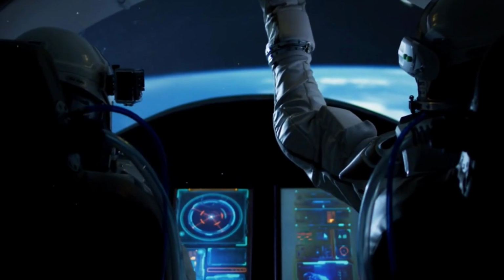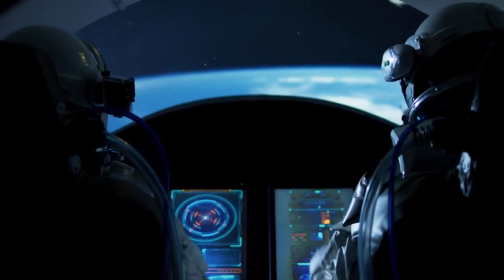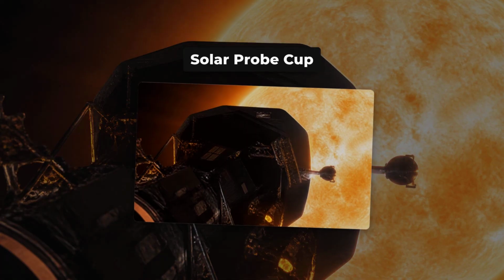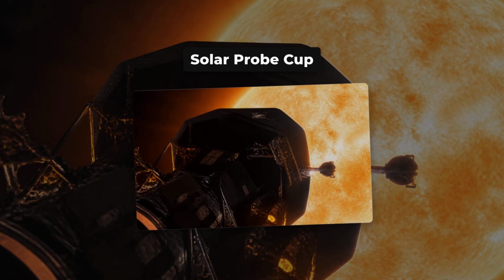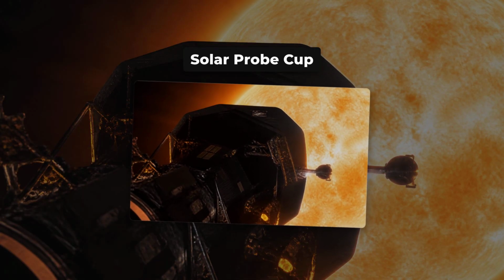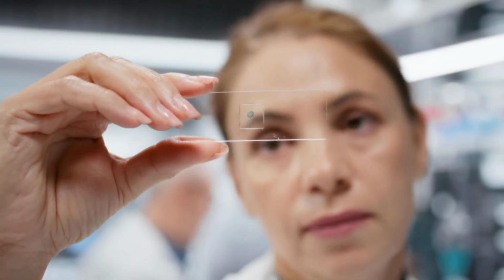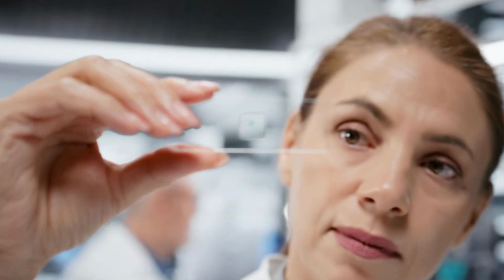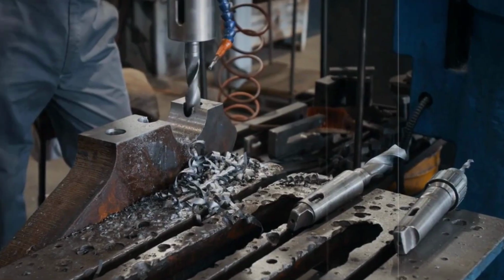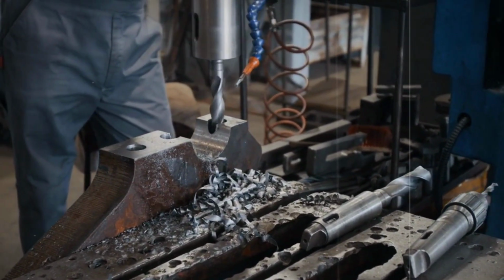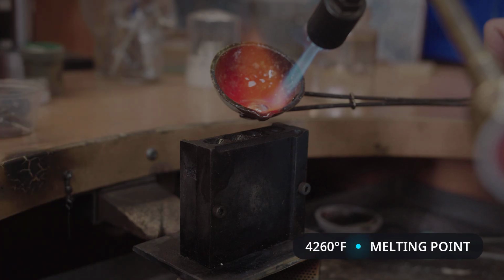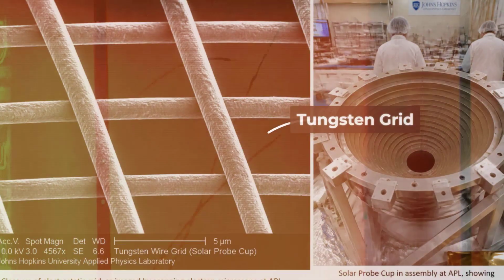To collect data, the probe cannot hide entirely behind its shield. The solar probe cup, designed to measure ion and electron fluxes, must extend past the protective shadow, directly into the unmitigated flux of the sun. To survive this exposure, the Johns Hopkins Applied Physics Laboratory turned to extreme metallurgy. The cup's housing is machined from a titanium zirconium molybdenum alloy, which boasts a melting point of 4,260 degrees Fahrenheit.